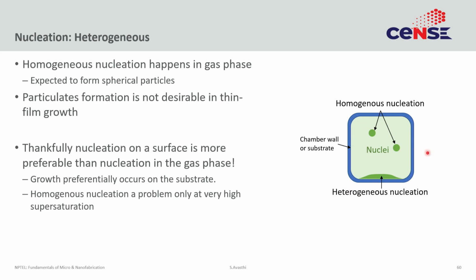And this is very, very important, because if you think about it, if you are doing, say, silicon deposition using silane, and if gas phase reactions start happening more than deposition reactions, then instead of getting a silicon film, you will just have a shower of silicon particles, right. So, silane will break down into silicon atoms, those silicon atoms will form these particles, and those particles will rain down on your wafer, but not give you a film. It does not happen because homogeneous nucleation is less probable, heterogeneous nucleation is more probable. So, you actually start depositing on the wafer before you start nucleating in the vapor.